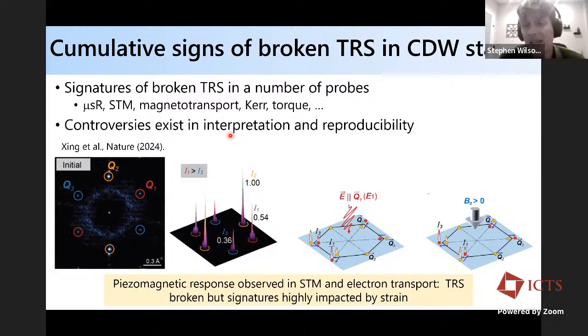And I can't go through all of the data, but I'll just suffice to say that there are many different probes that report signatures of broken time reversal symmetry, ranging from muon spin resonance (µSR) measurements to scanning tunneling microscopy and spectroscopy measurements, magnetotransport measurements, Kerr rotation measurements, as well as torque measurements in the charge density wave phase. But the majority of these are not without controversies, either in the interpretation of the data being generated from the sample, or the reproducibility of the effect itself.